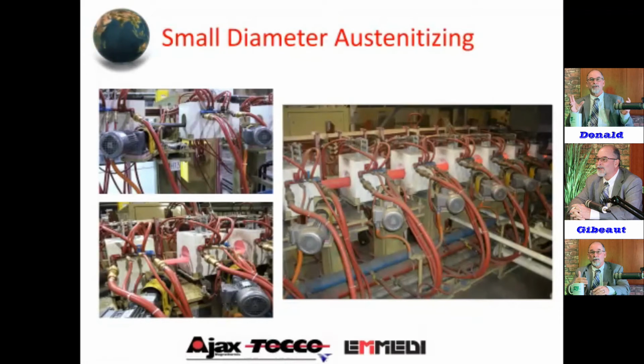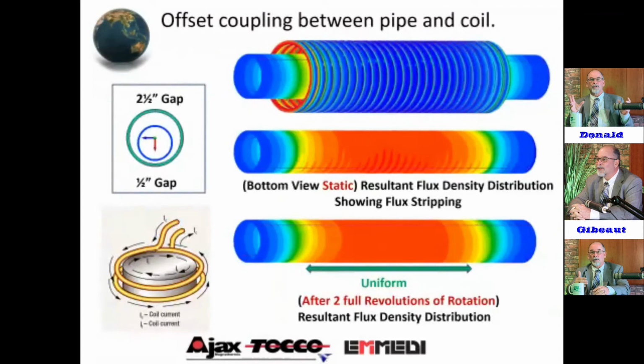Increased efficiency. So it's pretty much a wash, not a one-to-one, but pretty much a wash. And remember, the pipe is rotating as it's feeding, and that becomes one of the key elements. If you rotate 2 full revolutions in the coil, you have enough length for the throughput that you're running. But if you have 2 full revolutions, let's look at this condition of a 1/2 inch coupling at the bottom and a 2.5 inch at the top.